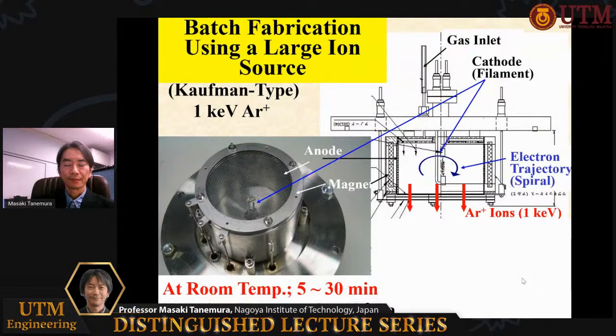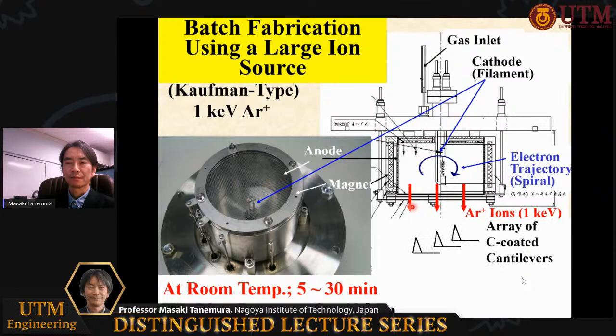This is the ion source. Very simple. Just a filament to emit electrons. Here, a magnet to enhance the electron trajectory, and an electrode. Argon ions come like this. If we put the cantilever like this, the carbon nanofibers grow like this. And if we put the cantilever like this, the carbon nanofibers grow like this.